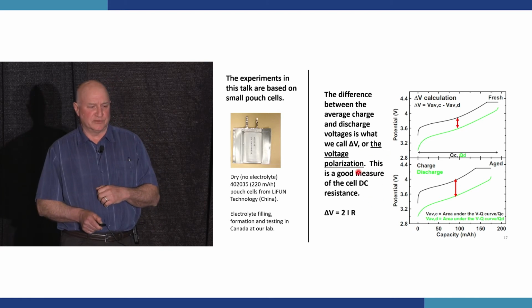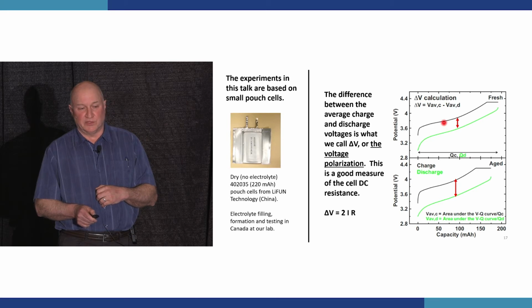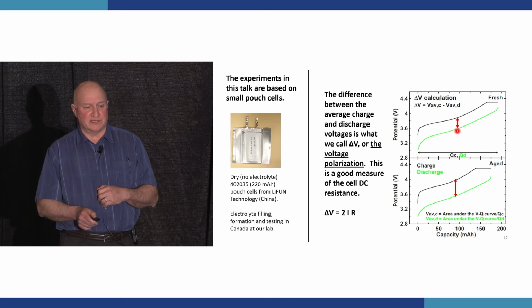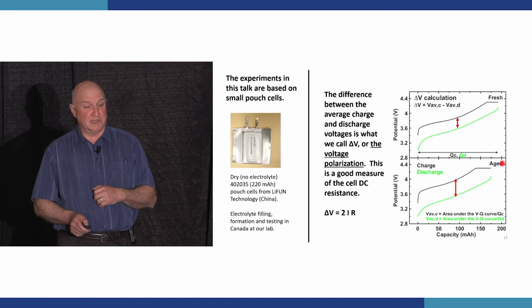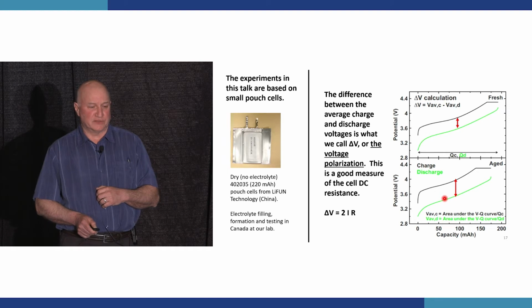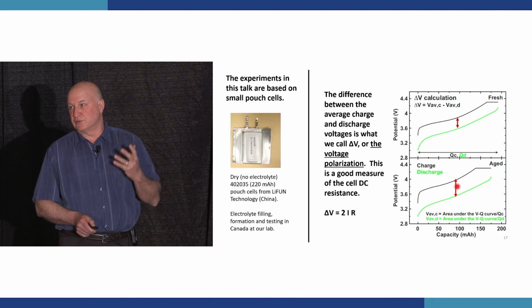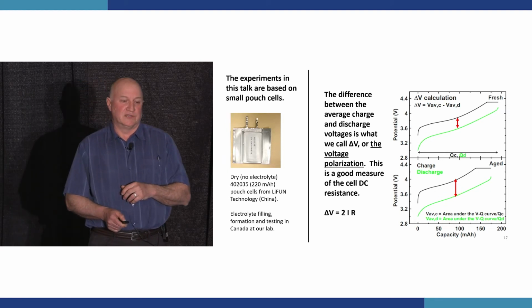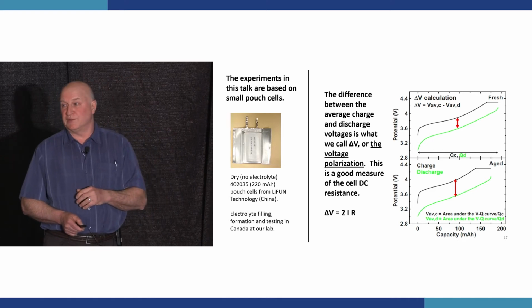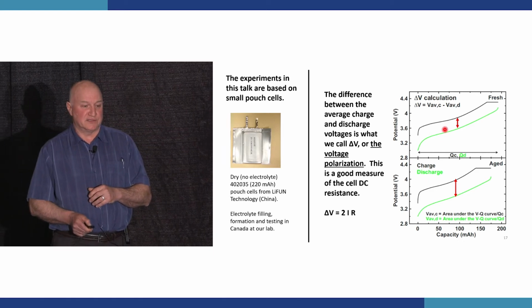And one of the things I'll talk about today and the data I'll show you is something we call the voltage polarization, or delta V. That's the gap between the charge and discharge curve shown here. So for a fresh cell running at maybe 1C charge and 1C discharge, the gap might look like this. And as the cell ages over time, it might take many, many years, the gap will open up. And this is a measure of the growth of the internal impedance of the cell. So we don't want impedance growth happening, so we keep an eye on this delta V.